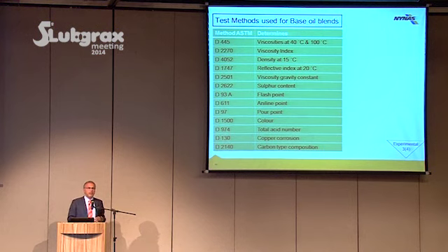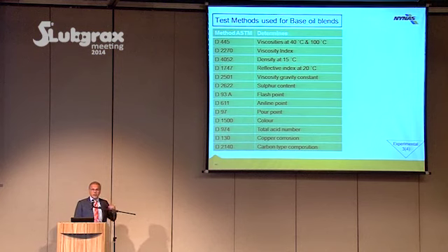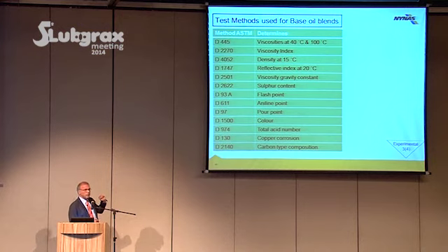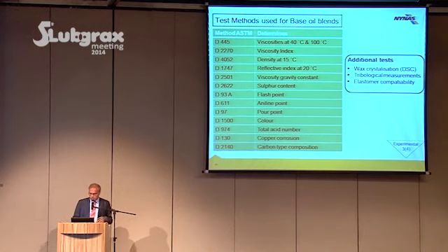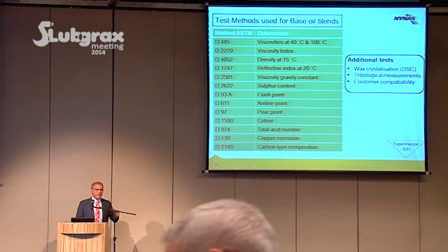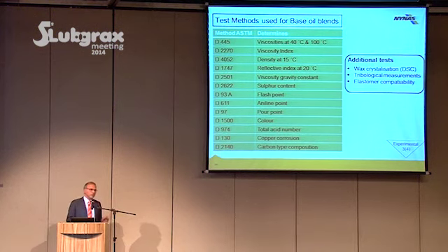These are the typical tests which a refinery normally carries out and offers to their customers. And that's why we did it, in order to have a reference to compare, or to refresh your memory, or if you want to compare with some current products, so it's easier. On top of that, we did some additional tests. Wax crystallization in paraffinic oil, wax exists despite the waxing unit. I will come back to that. Tribological measurement, we measure, as mentioned, the frictional coefficient of the blends compared with each other. Elastomer compatibility, how rubber changes when it comes into contact with the oil or oil and greases.